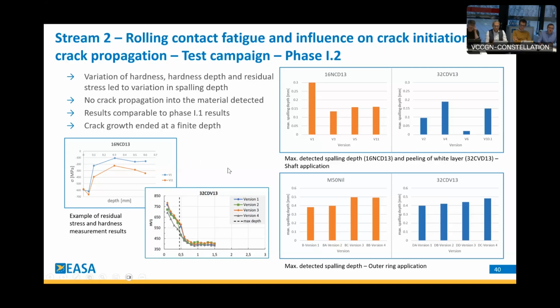On the right side, you see the evaluation of the maximum detected spalling depth for 16NCD13 and the peeling, as I mentioned, of the white layer for the 32CDV13. This is the shaft application. And we see some influence. You see it here for version 1, it's a depth of 0.3, whereas it's 0.1 to 0.15. You see also on the peeling of the white layer a difference.